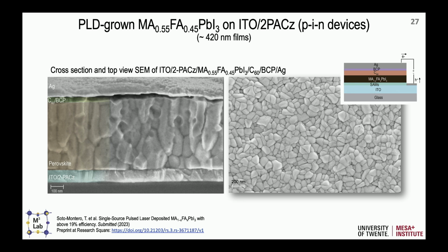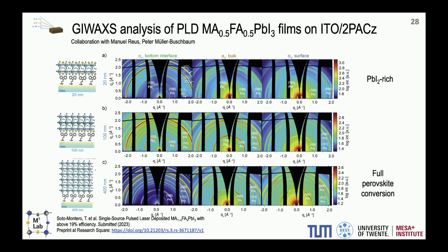So the first question is, how does it look if you change the substrate? The substrate has a strong effect on the perovskite, but you can see we have a nice, dense formation of the perovskite films. So that was already good, and also a little bit of columnar growth. We also wanted to know how it grows. I know this is a very full slide, but maybe what we can look at is what happens when you have a very thin layer.